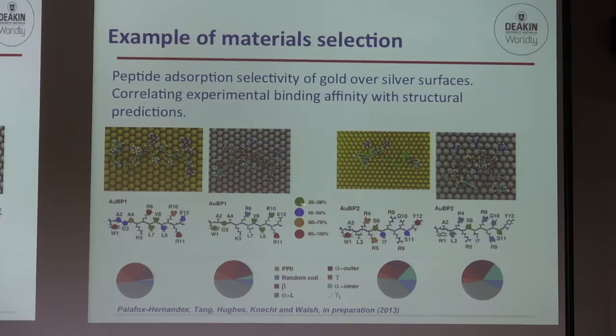And so what these dots are telling you is that the hotter the dot, basically the stronger the connection between the peptide and the surface. And you can see that this kind of map of the hotspots of interaction is very different between the two materials. So some parts of the molecule really prefer sticking to gold, but some parts prefer sticking to silver. And it's basically being able to unpick those threads so that we can dream up peptide sequences that have a better selectivity over these two materials.